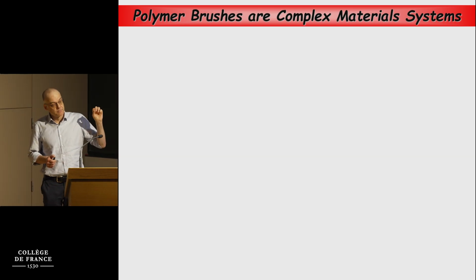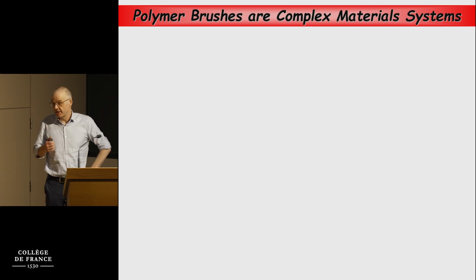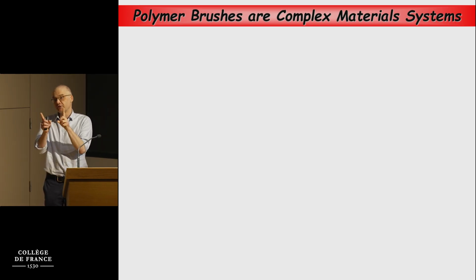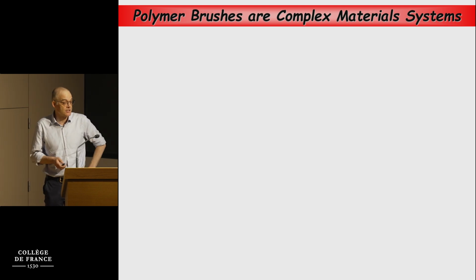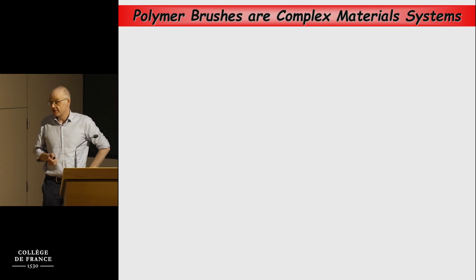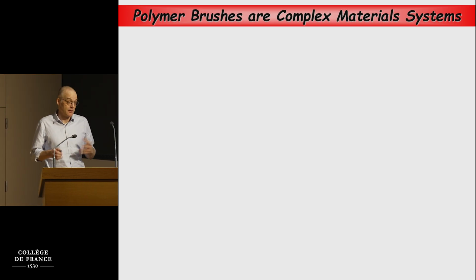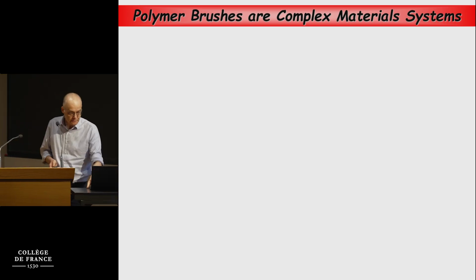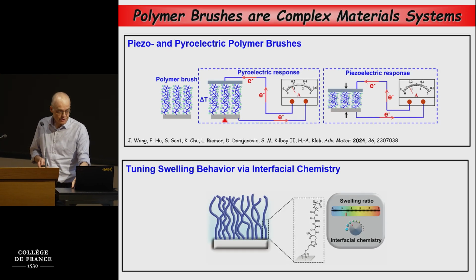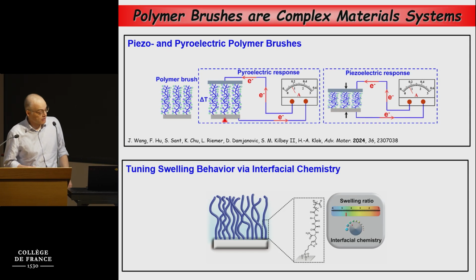We have polarized FTIR and also NEXAFS experiments to back this up that indicate that if you look at the alignment of the nitrile groups in these films, there is indeed a net alignment in the brush films grown via surface-initiated polymerization, whereas there is actually isotropic orientation of dipoles in these spin-coated films, which I think is very interesting. So this brings me already to the end of the presentation.